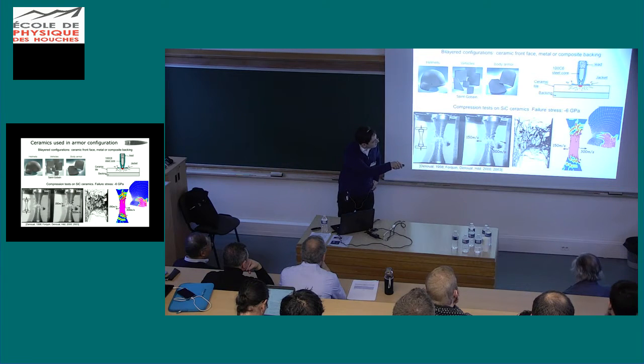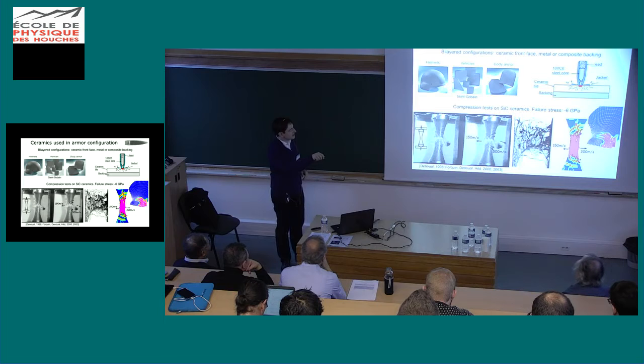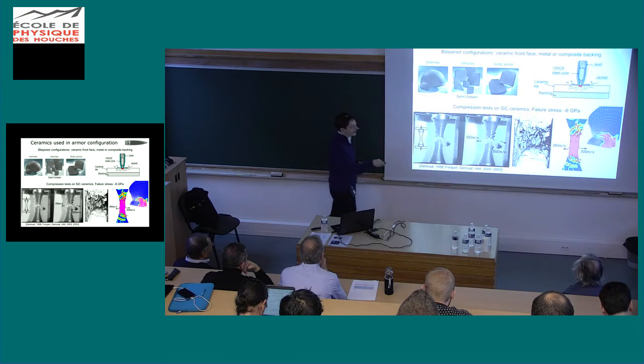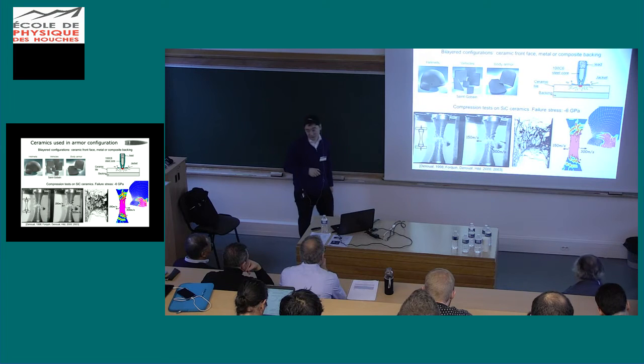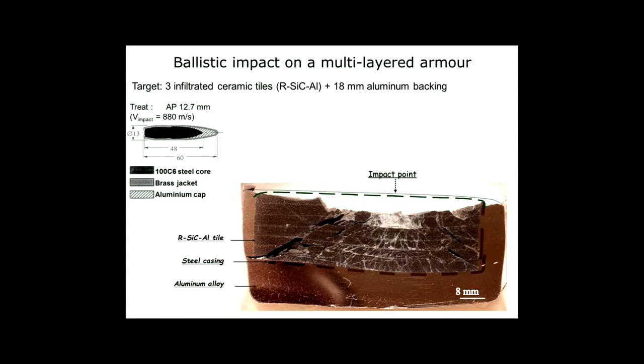And what is interesting is, as you can see in this numerical simulation, during the next few tenths of microseconds, damage skirts around the central part of the sample, and the remaining loading is transmitted to the intact part of the sample. That's why, in this part, stress goes much higher than 6 gigapascal. It's a dynamic process, and we can reach locally up to 12 gigapascal. And when you convert 12 gigapascal of elastic energy into kinetic energy, you get a new ejection velocity on the opposite part from the triggering point, that is 300 meters per second. So it's a dynamic fragmentation process due to a quasi-static failure at the beginning. Quasi-static loading, is what we say.